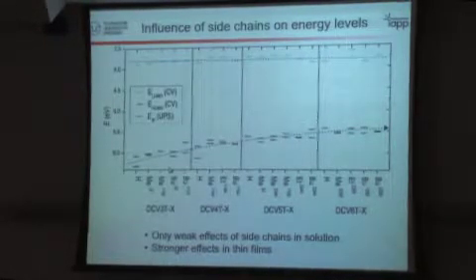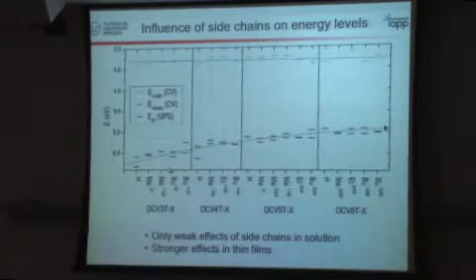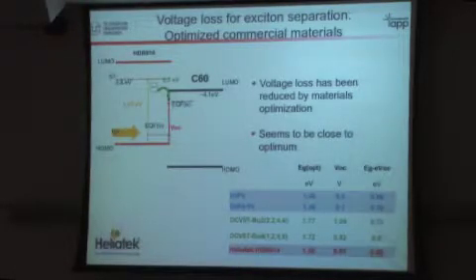And we have observed, I don't want to go into any detail, but you get completely different crystal structures depending on the side group, and it's not possible at the moment to predict that in any way. So although these materials should allow a systematic variation, in practice, when you really do it, you have an extremely complicated system.